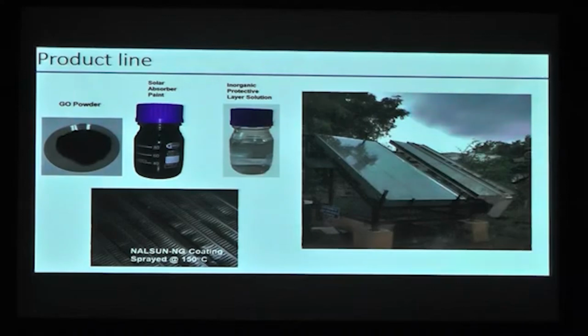The conversion efficiency of the coating is almost around 70%. Whereas compared to the Chinese evacuated tube collectors, which are recently available in the market, the conversion efficiency is only 55%. So the major advantage of using our coating is that the conversion efficiency is 70%. And based on the test results, we found that the service lifetime of the coating is more than 20 years, whereas none of the Chinese evacuated tube collectors can give that guarantee. They are not able to provide it, because this is a glass receiver tube and the damage is very much evident. So that is the advantage of this flat plate collector: the service lifetime is more than 20 years.